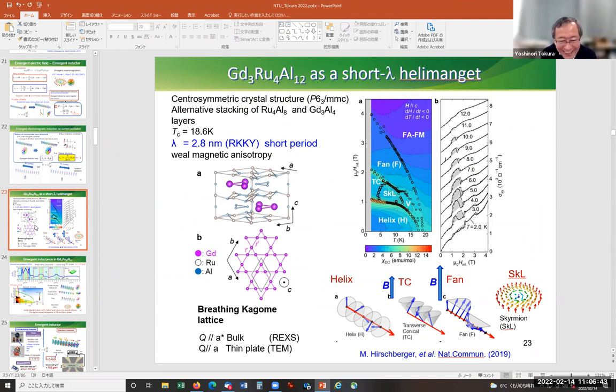Thank you very much. It's a very interesting, very important question. The skyrmion size is small enough, but basically this compound's band structure itself is heavily dominated by the ruthenium aluminum, large dispersing d electron bands. So, very briefly and intuitively, the carrier number is too high. So the ordinary Hall effect is very small. So that is no good. Nevertheless, we observed a huge response in three dimensions, but in the case of two, again, we need a two-dimensional system. And also high mobility, maybe the important point is the low carrier density system.